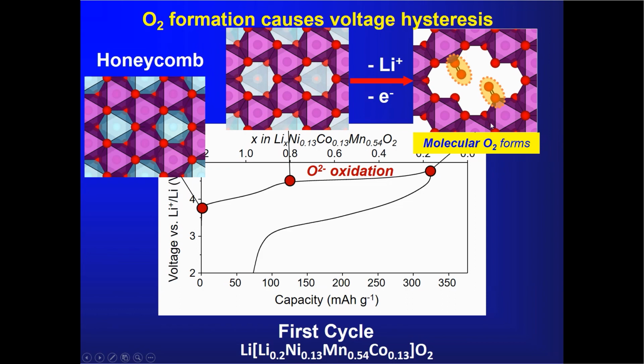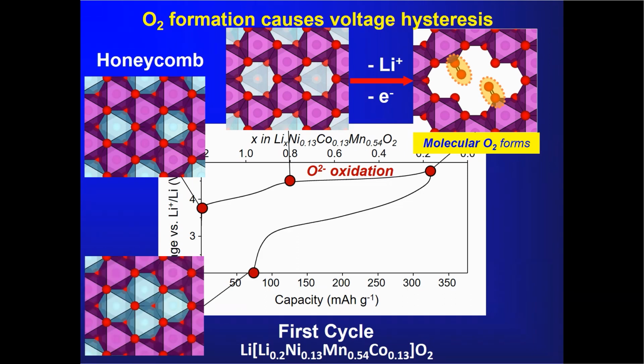I'm not saying this is the only one. This is just one possible model cluster that shows you what is possible. And I'll show you in a moment the DFT to support this as being an energetically favorable process. And then when you discharge and put lithium ions back into the transition metal layers, you do not reform the honeycomb structure. I showed you this before. There's no recovery of this honeycomb structure. What happens is you reintroduce the lithium ions, but into different sites now, filling these cluster vacancies and reducing the molecular oxygen back to oxide ions. So if you contrast the pristine and end of discharge structures, you can see that they're different, and it's reasonable that the energetics of these 2 structures would also be different.